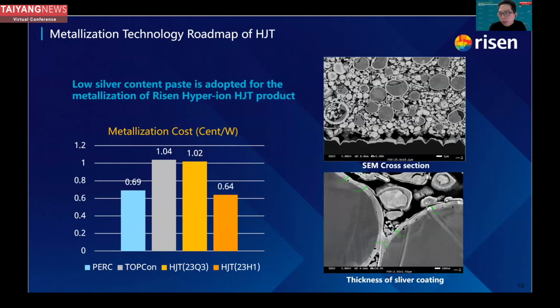Aside from the thinning of the wafer, we are also lowering the silver consumption by adopting low silver content paste. On the right, it shows some SEM cross-section pictures of the low silver content paste. As you can see, for this silver content, two materials were adopted. In the middle, we see a shell which is silver, and inside the shell is copper, which is a low-cost material.